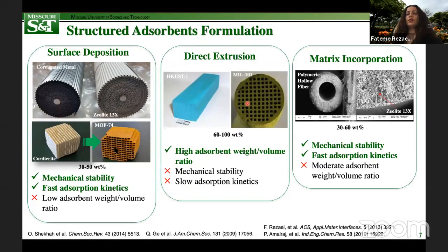The good mechanical stability results from the elastic behavior of the polymer matrix that imparts some good mechanical strength, as I mentioned. Obviously, considering all the three approaches, there are some trade-offs between the properties, structure, and the adsorptive performance of the structured adsorbents fabricated by these techniques that need to be carefully considered and managed during formulation, and also during the choice of the formulation method.